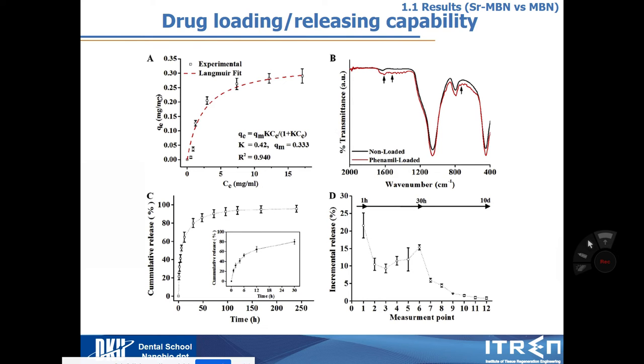So it's a little bit complicated, but as I increase the concentration of phenamil, I can load a certain amount, absolutely 30% maximum. And after phenamil was loaded in strontium MBN, I checked whether phenamil is located there or not. When you see this peak, this is the phenamil peak, so I can say phenamil is loaded in our nanoparticle. And then how do they release the phenamil? I checked they are released quite fast over 2 days and start to release slowly after that. So this release pattern is fast initially, slow later.